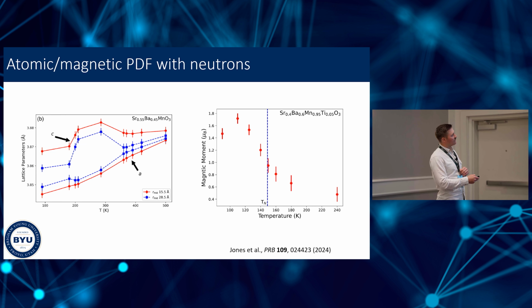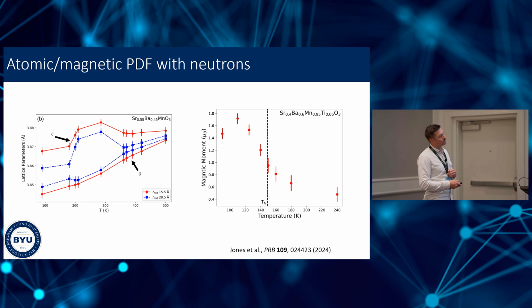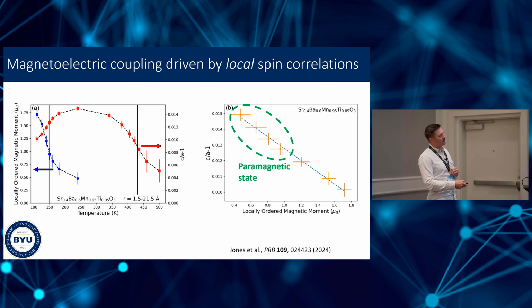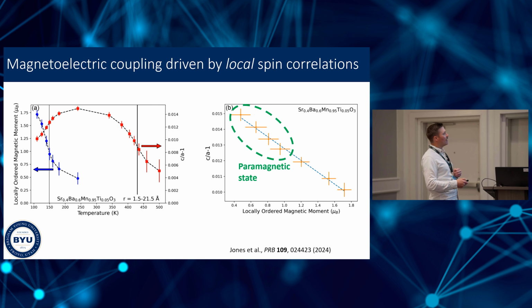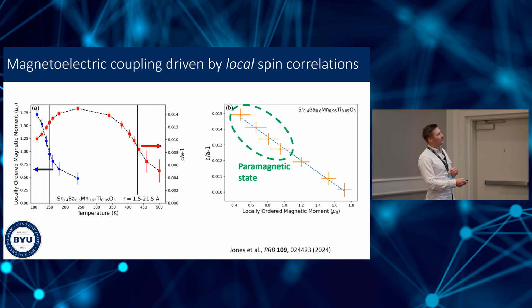But we're sensitive to these changes in the lattice parameters, which again represent the ferroelectric behavior. The larger the C over A ratio, the greater the electric dipole moment. And then here we have the local magnetic order parameter determined from our magnetic PDF fits. The key observation here is that those correlations, the local magnetic correlations, do not disappear above the Néel temperature, but instead persist into the paramagnetic state. So let's look at those together. Here's the C over A ratio. Here's the local magnetic order parameter.